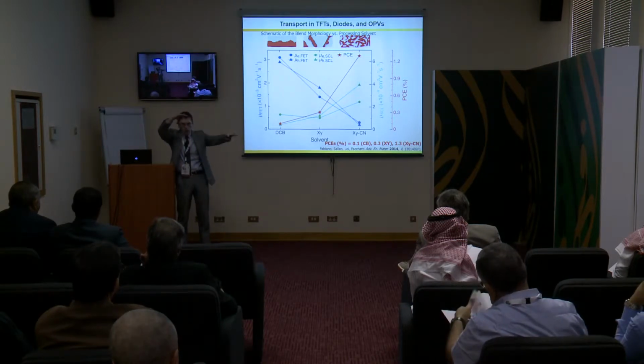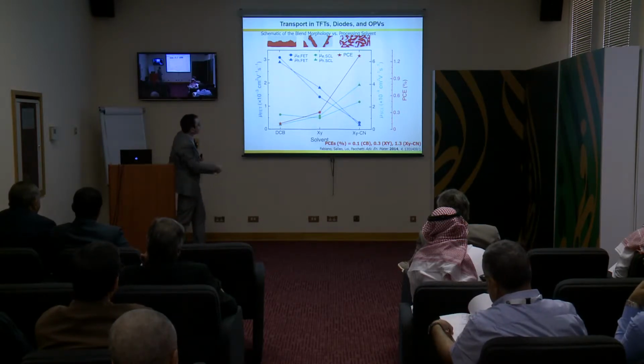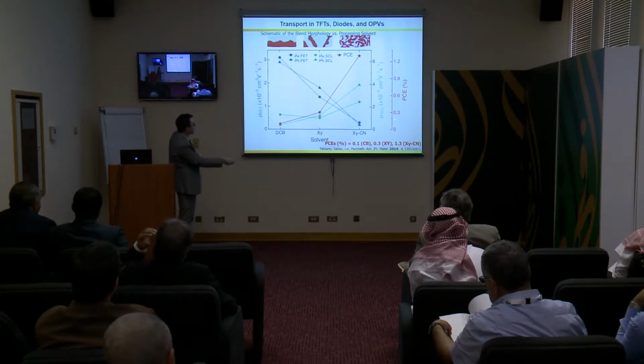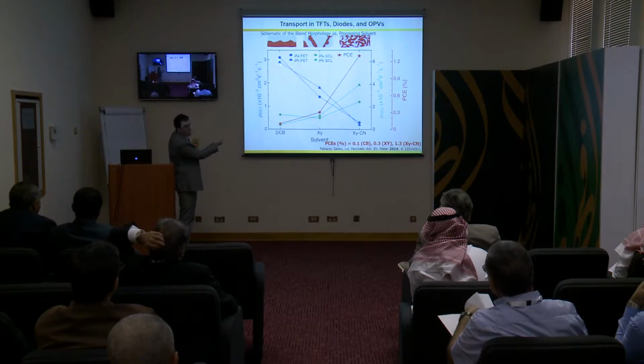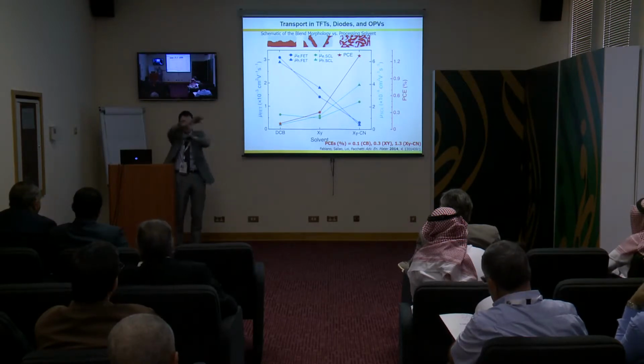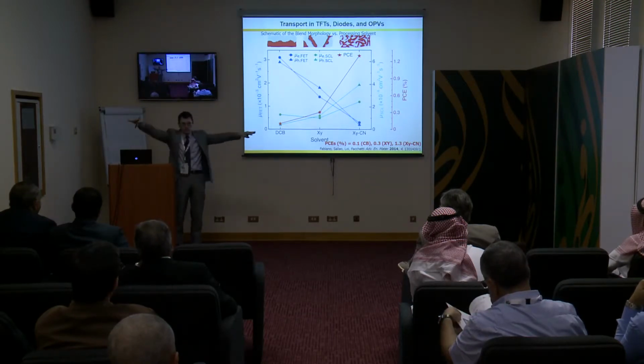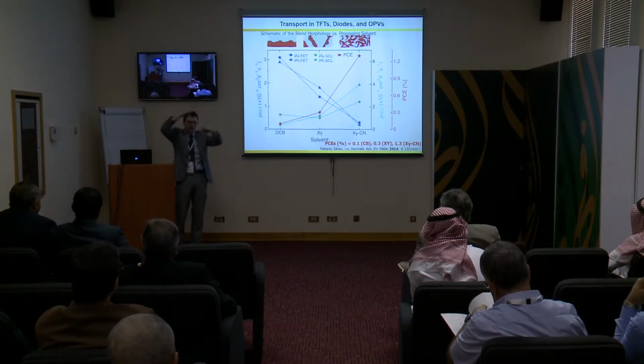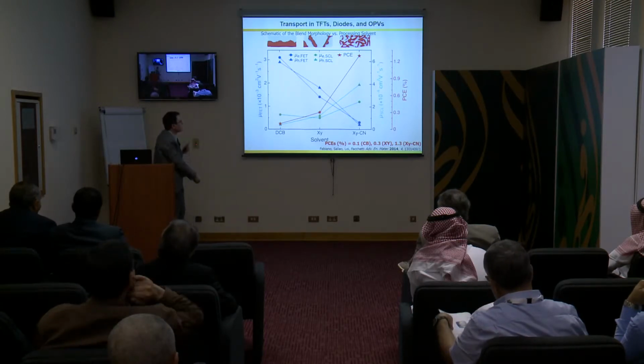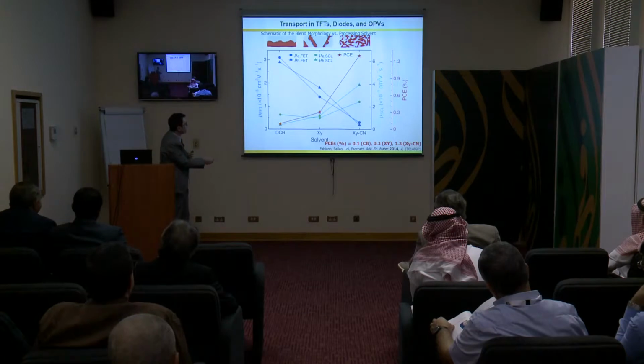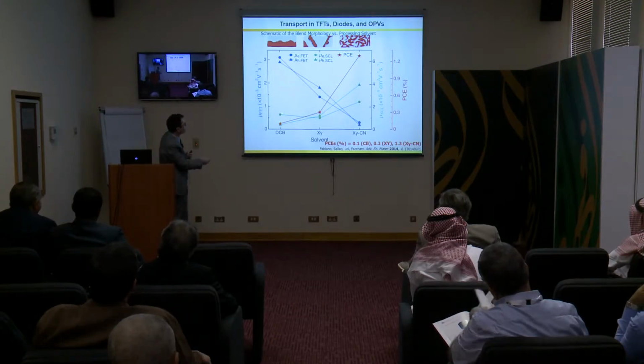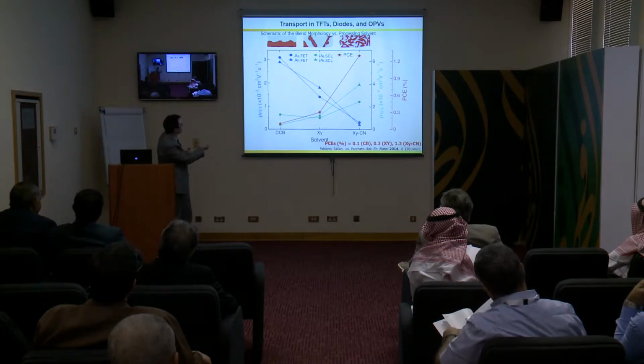The P-type polymer is at the bottom. So if you look at the PCE of these blends in red, it is very, very poor. The field effect mobility is good because you have transport in this direction, okay? So you have phase separation, which is great. But in the diode direction, you have only a very small interface, so the PCE is very, very low. The diode mobilities are very, very low, and you have good field effect mobility.